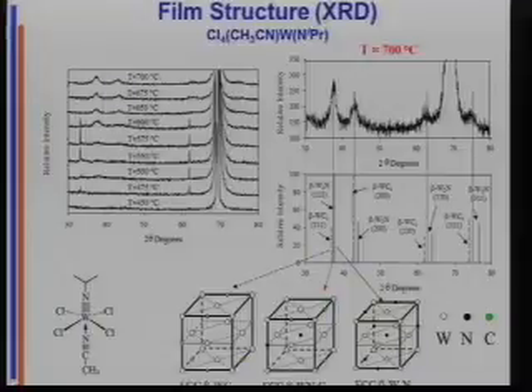Well, at this point, we'd identified the material, at least the crystalline bits, and it wasn't quite tungsten nitride, but right about that time, somebody published a paper on how fabulous a barrier material the ternary nitride carbide phase was. Fabulous. We win. We're going with it. Guess what? All this time, we really wanted to grow that ternary phase because that's such a great barrier material. Isn't that how your research works? Yeah. All right. So that's what we're growing.